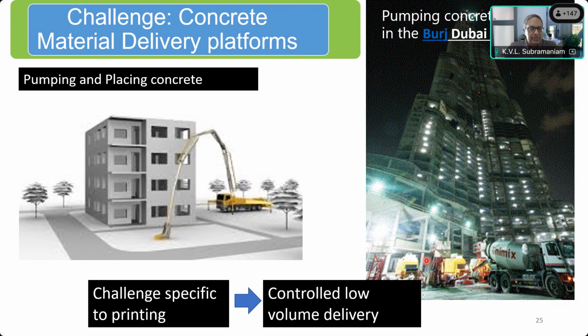And as a consequence of this, because of limitations of this controlled low volume delivery, today we are limited to using concrete with small aggregate size. What we are able to print as concrete today is limited to about 4 to 6 millimeters in size. Now, you know that regular concrete, we use 20 millimeters aggregate.